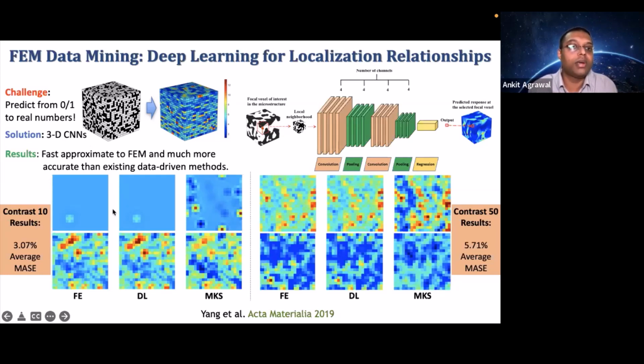I'll not go into too many details here. They are in this article, but just to give some results on 2 different contrast data sets. Contrast is basically the ratio of the Young's modulus of the black and the white phase. And you can imagine higher contrast means a more difficult data set to predict. This was in collaboration with Surya Kalidindi's group at Georgia Tech, and we were told that these are very high contrast values. Most of the existing models can barely work with contrast 2 or contrast 5. So 10 and 50 are really very high, and most of the existing models would fail.